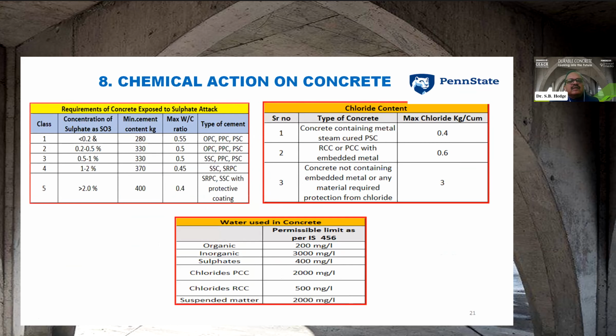And second, we will go to the chemical action on concrete. If you look at this table, different concentrations of SO3 are given for 5 different situations, and the required minimum cement content has been mentioned with maximum water cement ratio, and what type of cement is to be used has also been tabulated, and you can see by yourself.